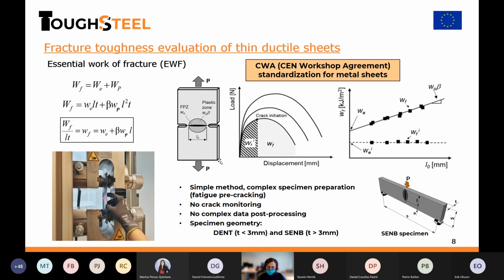One of the first things we can see, and that we have already commented in previous questions, is the thickness of the material sheets. Usually, when using thicknesses of less than 3 millimeters, we will use DENT specimens in a tension mode. But when we want to perform a test with more than 3 millimeters, we will use SENB specimens, single edge notch bending. As its name can tell, it's for bending process. And here we can have these two kinds of geometries. Usually we will use the DENT specimens, and one of the things we need to take into account in this methodology, that maybe it's the most complicated, is when